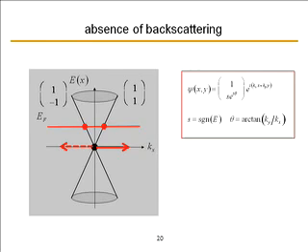Could we reflect to another valley? Another valley would be located at a big k distance away. So again, it would take a very rapidly varying potential in order to do that kind of transition between valleys. Now, there are mechanisms. I understand that surface edge roughness scattering varies on an atomic scale, and that can give you a perturbing potential that's rapid enough that it can flip and cause backscattering. But when we think about phonon scattering or ionized impurity scattering, we expect the backscattering to be suppressed.